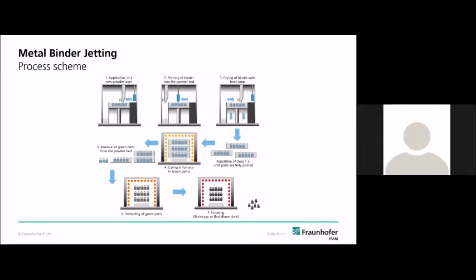And these so-called green parts are then, in step 6, put into another furnace and are debindered. And in the same furnace, they are sintered to either full density or they are only pre-sintered. And during this last step, number 7, we have a certain shrinkage of the parts, so the parts in gray are still bigger than those in black. This is intended. The parts become smaller after sintering.